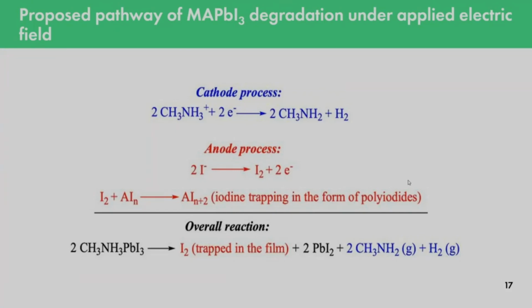And this also can probably be the new particles that we observed on AFM microscopy along the anode, which also confirms this suggestion. So the main conclusion made from this is that the major part responsible for the complete degradation of the device is a reduction process of the organic part, which leads to some volatile products that leave the film. And if we somehow try to capture these products and keep them in a closed volume, then probably we can try to make the process reversible, or to at least stay in some